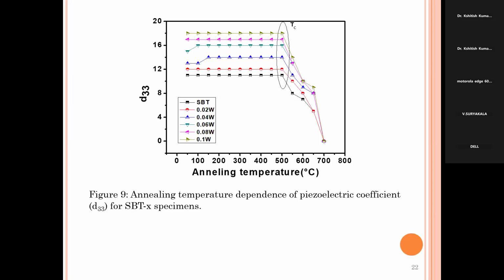So here I can say that we can find out up to room temperature to 500 degrees centigrade. So we got the constant piezoelectric property, meaning the d33 value is constant. After that, the d33 value gradually decreases. So that means we confirm the thermal stability of the material, that the material is sustained up to the transition temperature, and we can also use the material for high temperature piezoelectric application.